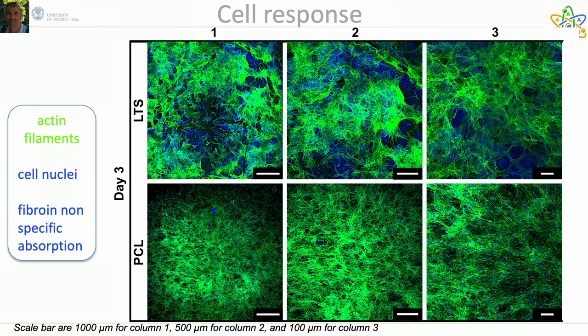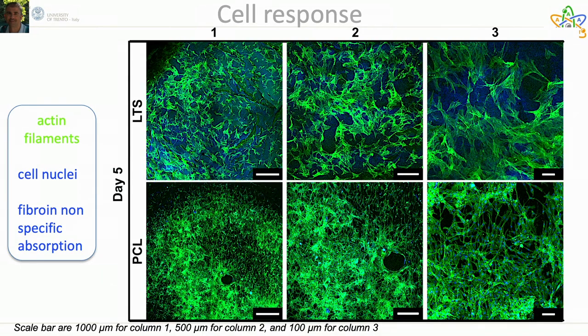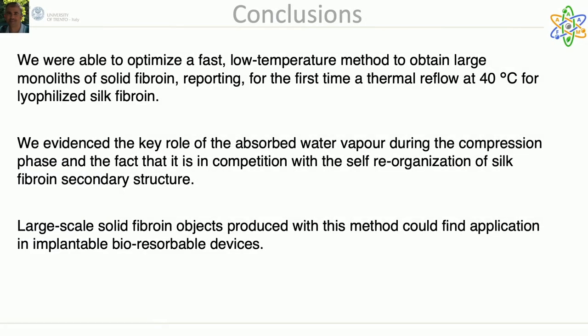This behavior can indicate that since low-temperature sintered fibroin samples are made of protein, their surfaces offer more adhesion sites to cells, improving the mechanism of interaction between cells and surface. This holds great potential in the design of a microscale scaffold for various tissue engineering applications. As a conclusion, I hope to have demonstrated the possibility of optimizing a fast, low-temperature method to obtain large monoliths of solid fibroin, reporting for the first time a thermal reflow at 40 degrees for lyophilized silk fibroin.